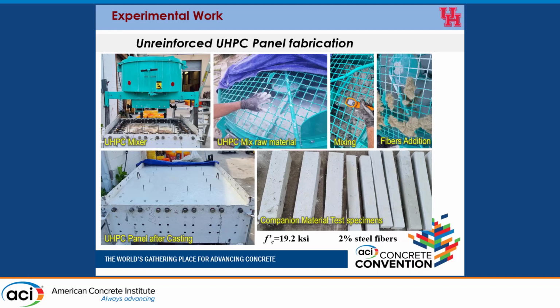In addition to the material test level specimens, the steel fiber content was 2%, and the compressive strength of the UHPC material after 28 days was 19.2 KSI.